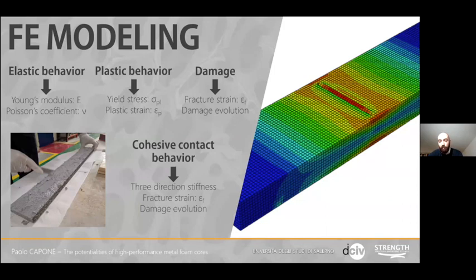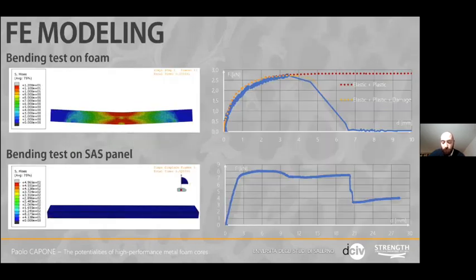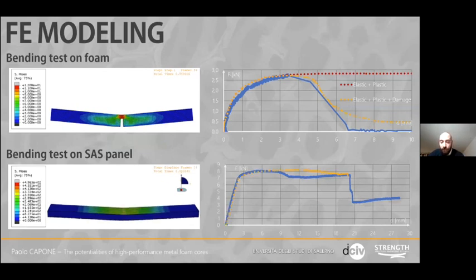Only for the aluminum foam, a damage law has been defined, providing the damage initiation point and its evolution, and then the contact between skin and core has been defined with a cohesive behavior, where the required parameters are the stiffness in 3 directions, the damage initiation stress, and the damage evolution. And we can see the results of the finite element modeling with a quite perfect overlap with the experimental ones.